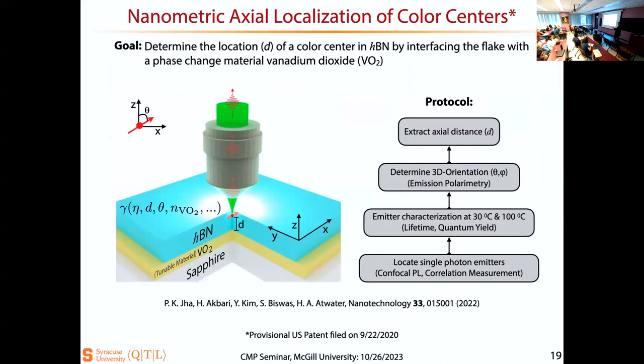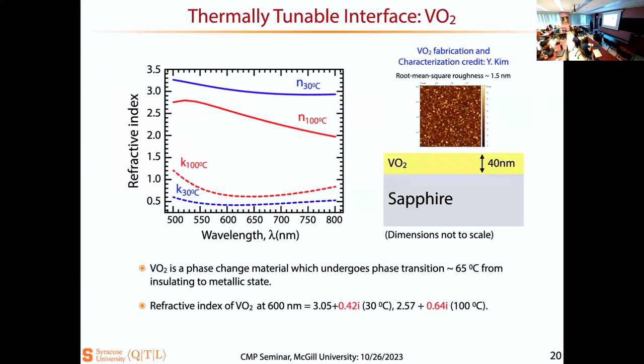VO2 is a phase change material whose refractive index changes if you make a phase transition around 65 degrees Celsius. At room temperature, it acts as an insulating state. The moment you make a transition from 65 degrees Celsius or above, going up to 100 degrees Celsius, it acts as a metallic state. And you can clearly see how the refractive index changed, especially because one of our emitters was at 600 nanometers. But this is a very lossy material, and this lossy aspect has some challenges in finding where those color centers are. If you find a color center very, very close to the VO2, it's highly unlikely that you will be able to measure it because of the quenching of the emission due to the loss of energy there. That sets the limit on the closest you can find a color center to the VO2. So we found a solution: what if we can find a material which is really dielectric, less lossy, and use that?